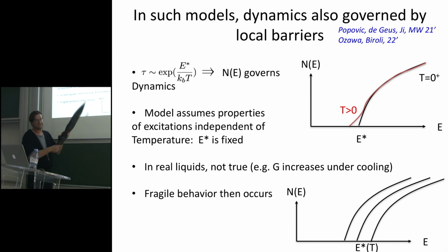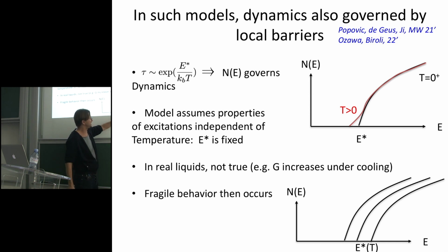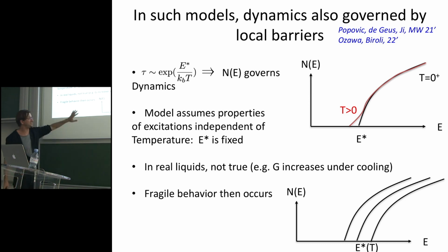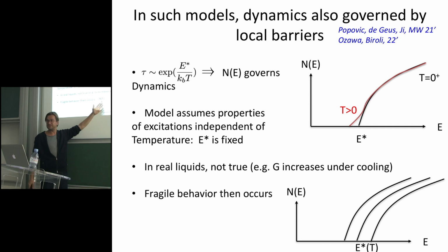Now, this is a very simple model, and E star is actually not dependent on temperature. If you want, it's a model of strong glass. But that's because we're assuming that the properties of excitations are always the same independently of temperature. I told you real fragile liquids, for example, have a shear modulus that increases significantly under cooling. So the scale of elastic energy should increase, and phenomenologically, E star should increase, right? So in this more realistic view, the density of states will shift with an E star that grows under cooling. This is very consistent with the first finding I showed you in the first part of the talk. If you put interaction between local excitations, you still have that local barriers control the dynamics.